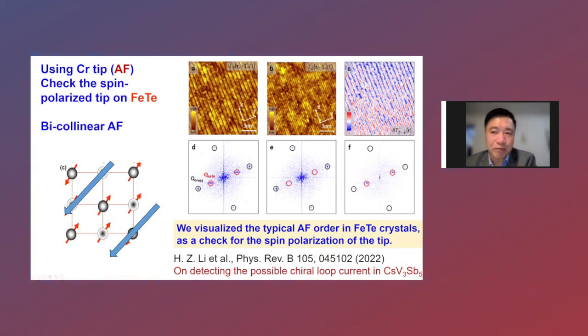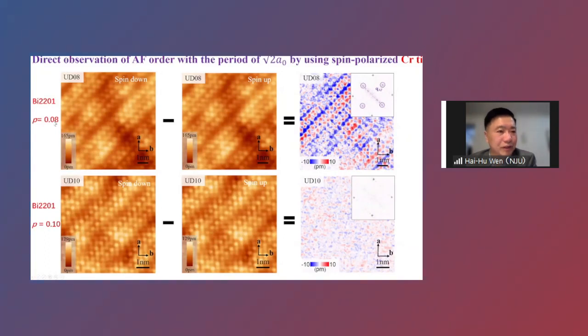And by doing the Fourier transform, you can clearly see this spot. This is due to the typical bicollinear antiferromagnetic order in the iron telluride. So that's a check of the tip. And then we measure on this so-called 8% doping and 10% doping.